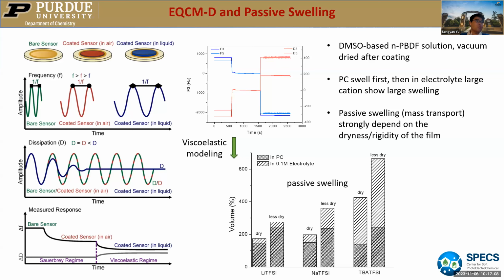A second approach is to use EQCM-D. I think many people are familiar with this. We coat the polymer onto the sensor and monitor the frequency change and the dissipation change during the process from air to electrolyte, and then with electrochemistry. I use the viscoelastic model to model this data, because the Sauerbrey model for rigid polymer can underestimate the thickness and the mass change.